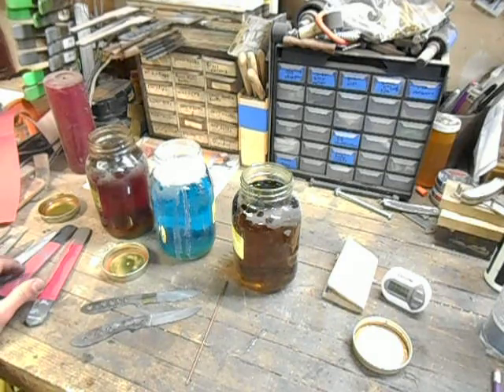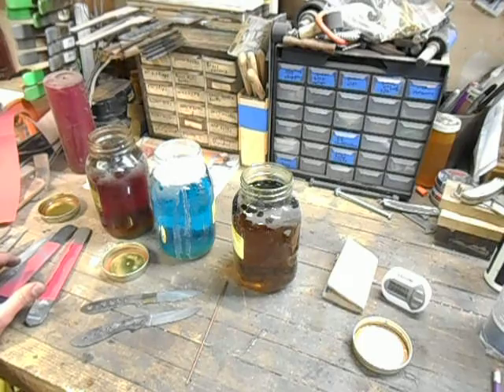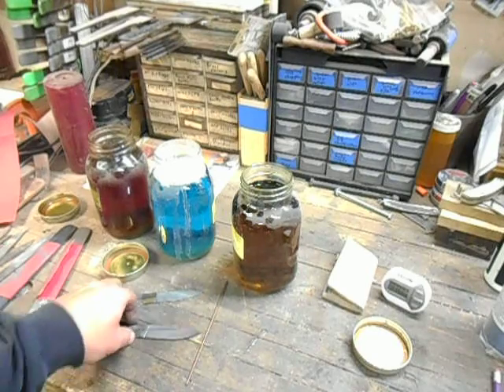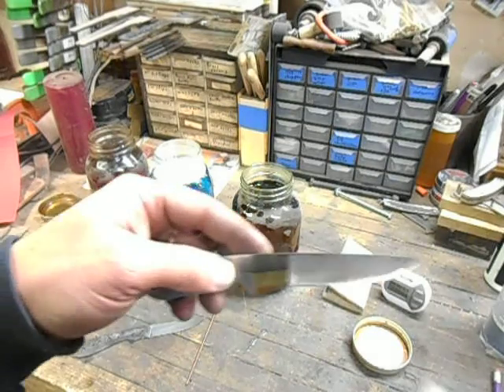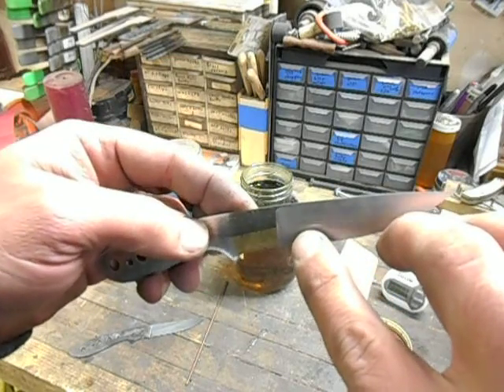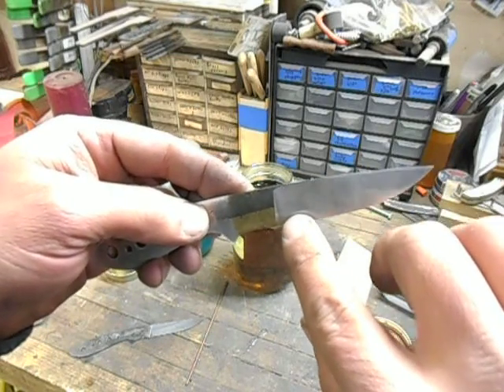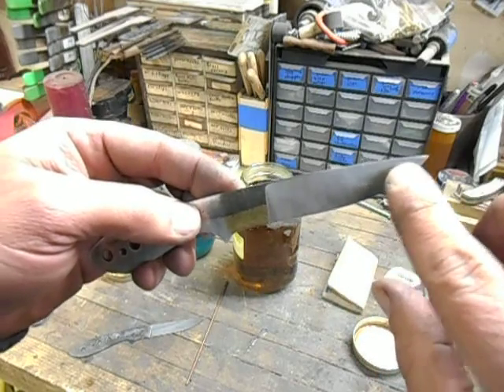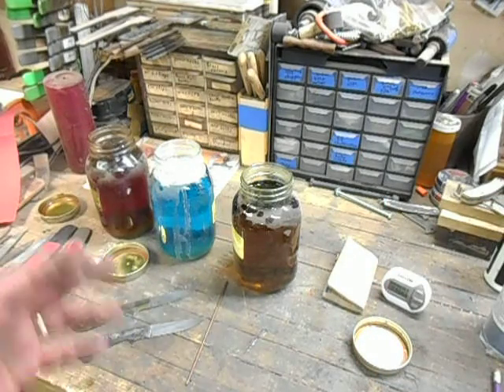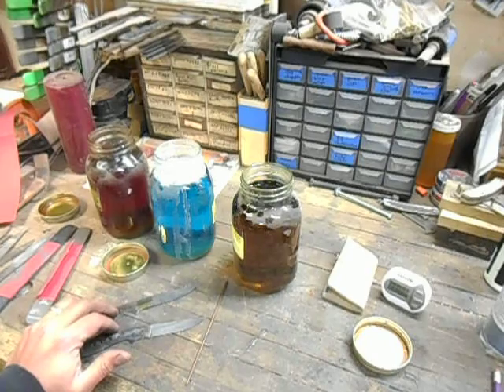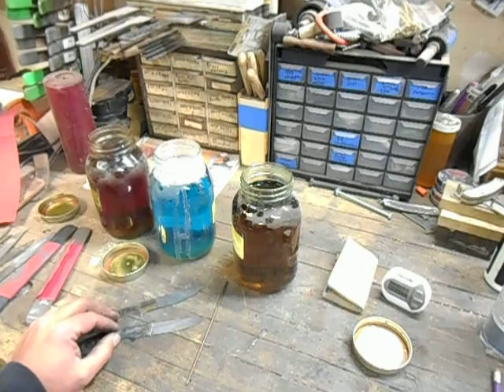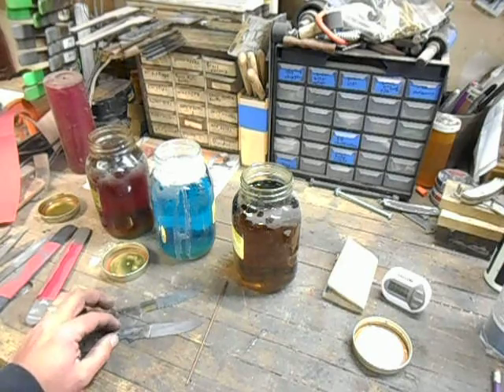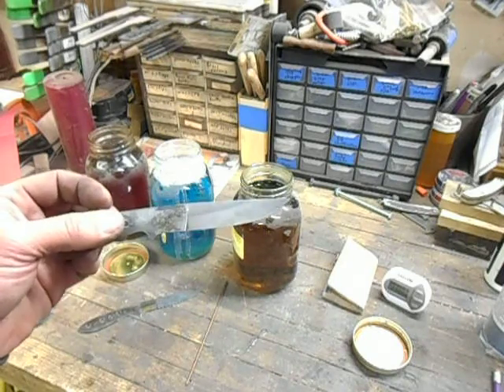Also, a lot of blades that the maker says were fully hardened, not with a differential heat treat, a lot of times, if you see little glints like that in the blade, even on a fully heat treated blade, you'll be able to see a hardening line in it sometimes. So anyway, keep an eye out for that. Once you get used to looking for them, you'll see them on an awful lot of knives, and sometimes they're not in the right spot they're supposed to be in, which is why I like the etch so well.